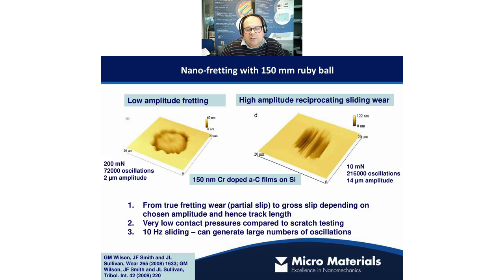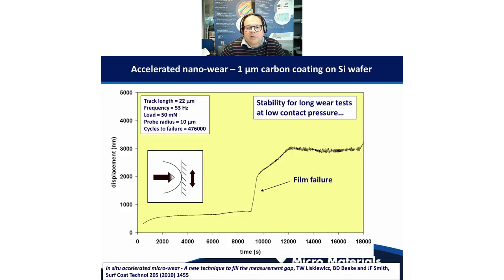And in this test, we've reduced the contact load, so now it's going to be easier for the ball to slide relative to the surface, and we've increased the amplitude of oscillation, and now we're getting a full gross sliding type contact. And you can control your amplitudes from anything in between. An interesting point to go to is an amplitude where you get some sliding, but you don't fully expose the wear track, and you can end up with trapped debris, which works as extra abrasive particles. You get this kind of third body erosion type test, which accelerates wear rates further. So you can simulate a large number of real world conditions by adjusting your test conditions accordingly.